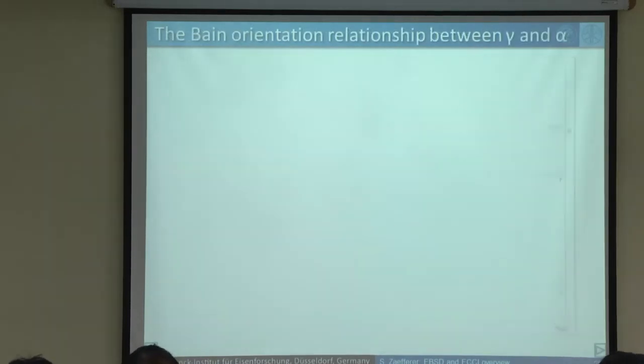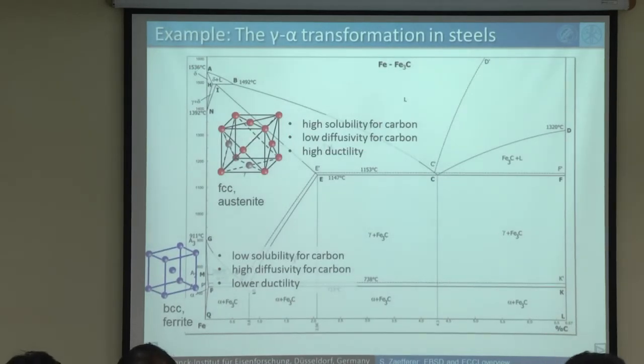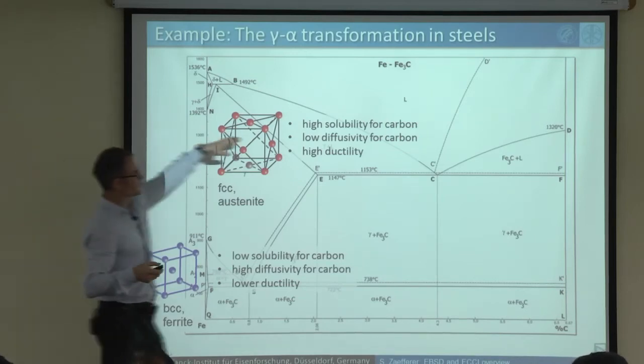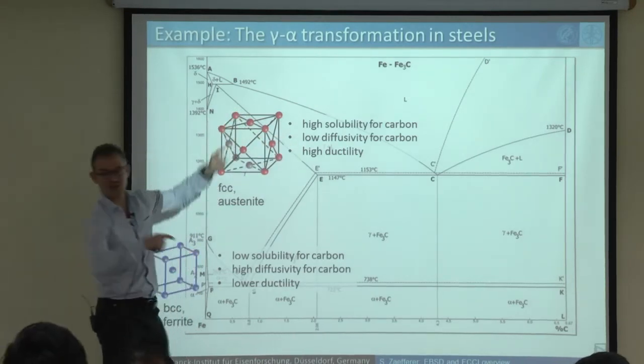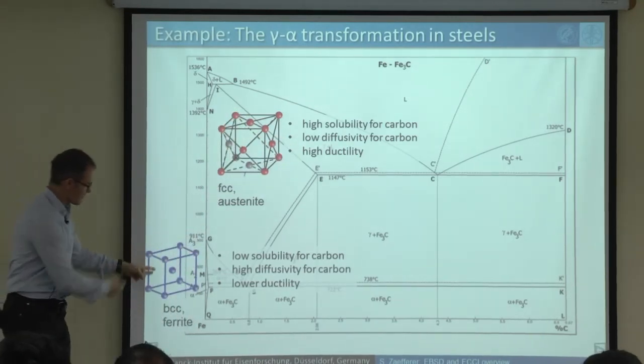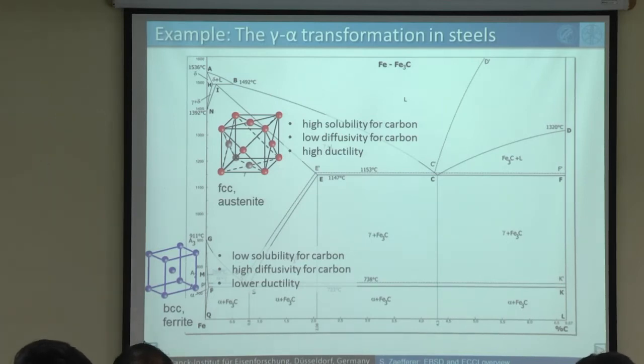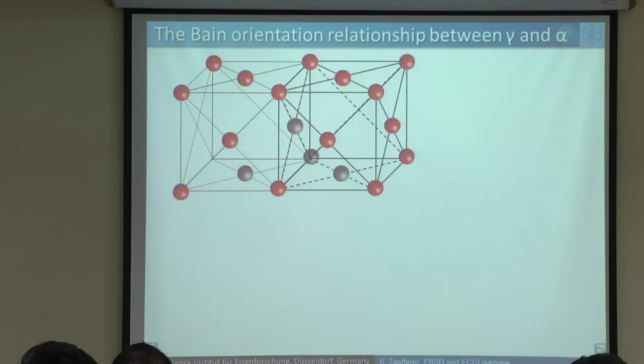So, one thing is, of course, the transformation from here to here. When you cool down quickly, you get a martensitic transformation. Yeah? And this martensitic transformation means the carbon diffusion will not happen, the austenite will just transform in a crystallographic manner into the BCC, into the martensite. And this happens always, or often at least, when you take a high temperature austenite and you quickly cool it down. And what happens then is actually the following. This is the FCC structure here, the FCC high temperature structure. And now inside of the FCC structure, you see already the BCC structure.